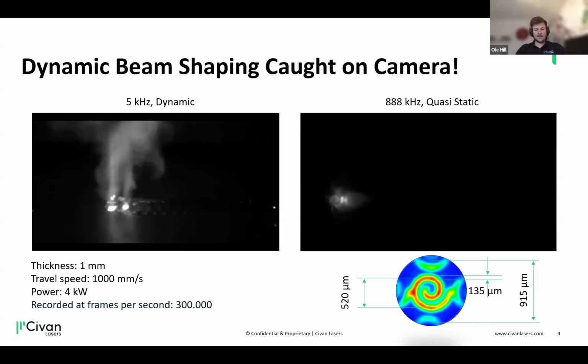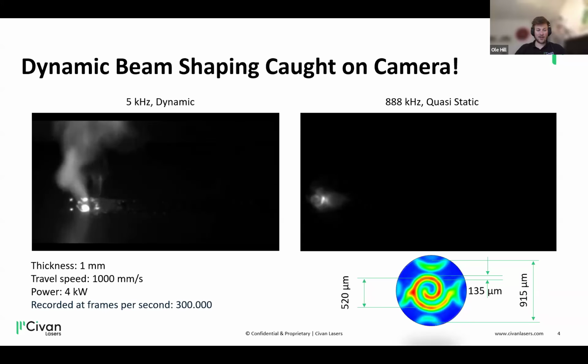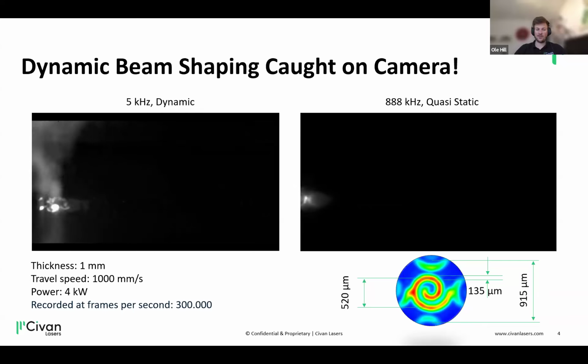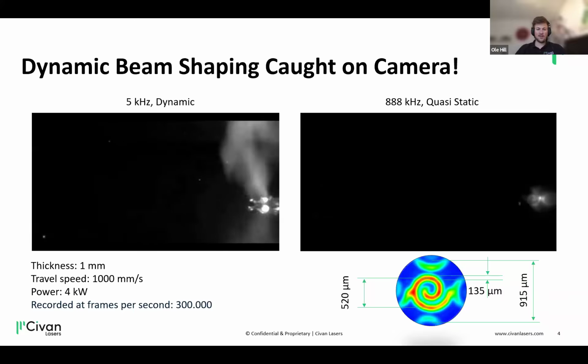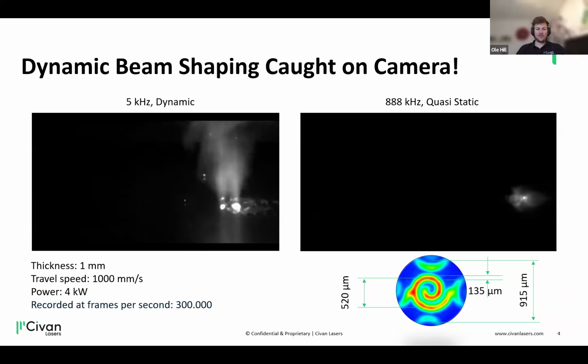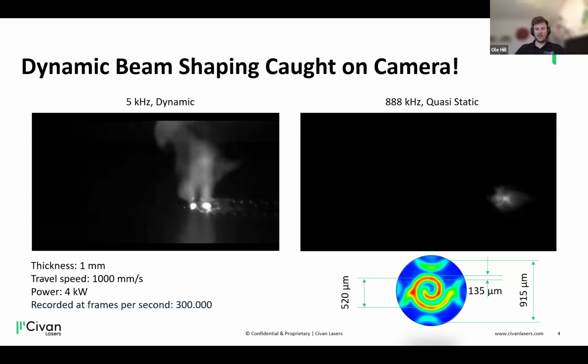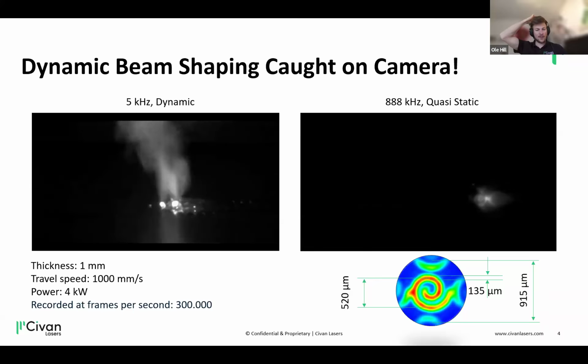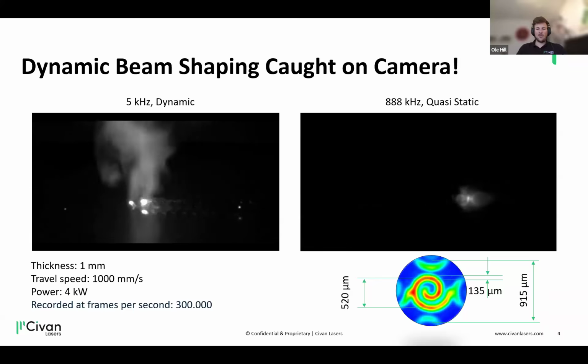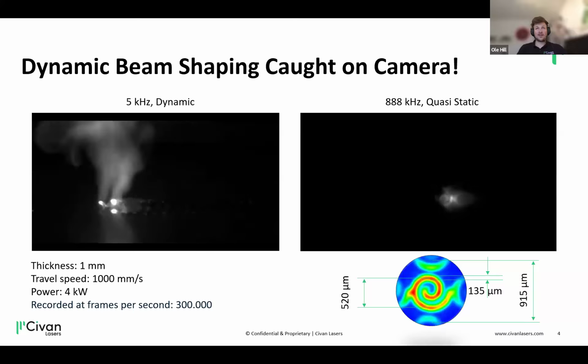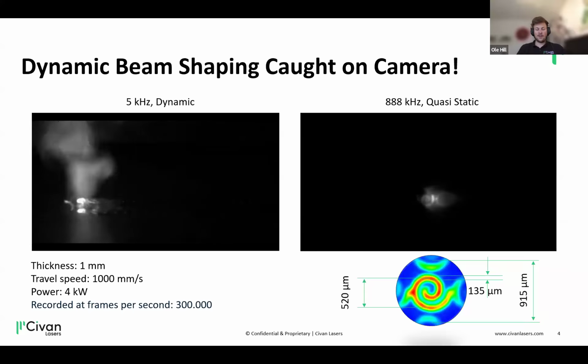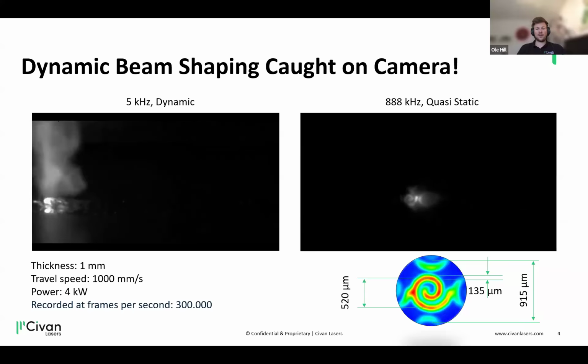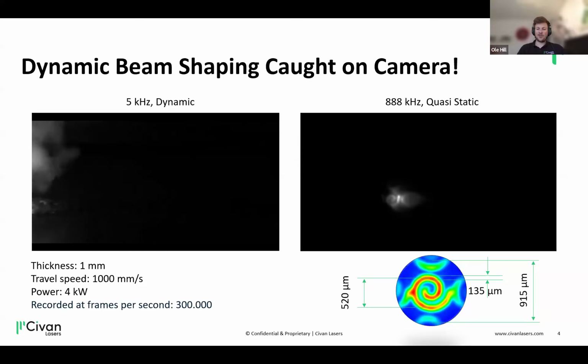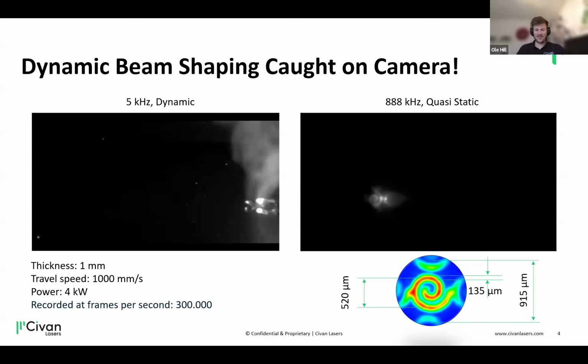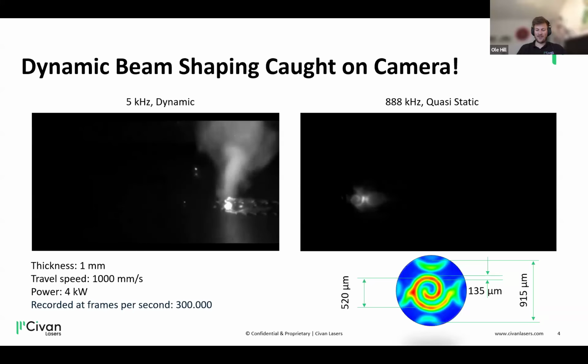Each of these regimes has different applications. For die-cast, we actually use both. First, we do a weld we call the penetration weld, which goes as deep as we want in a butt joint configuration, for example. And in the second pass, we go over the piece and over the weld seam in a static way at 888 kilohertz, which smoothens out the surface in a very nice way.